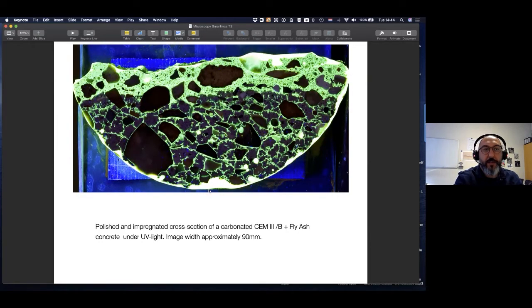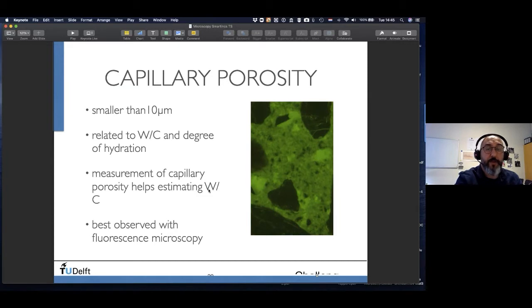You can do further things with UV lights. Applications: you can observe cracks, increase in capillary pores. Here you see just a polished half core, to examine the cracked microstructure. You can also observe capillary pores, but of course, optical microscopy is known to have relatively low magnification, low resolution. So it's really hard for us to observe pores smaller than 10 micrometers. And that's the reason we cannot see those super tiny capillary pores individually, but we can see their effect. So how much green light we are seeing.